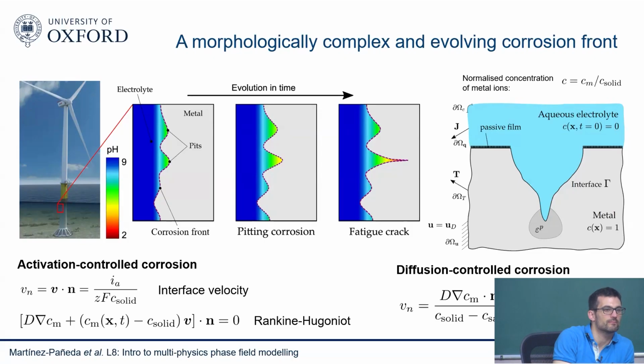A small follow-up: the depth or the amount of electrolyte you have on a wind turbine would not typically be a bulk solution. Some of your underlying physics may or may not be consistent in the case of a wind turbine. Because it's atmospheric, the film thickness of electrolyte that you have on the turbine is small. You have a change like here, right? This is what you mean? So you will have a change from bulk to local defects. So they see pitting and this kind of thing. These are carbon steel, so they pit pretty quickly. But since you are solving the electrochemistry, you will see that change in local conditions. So you will know what happens, what is the condition near your pit.